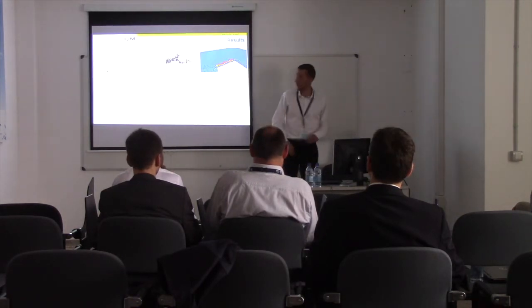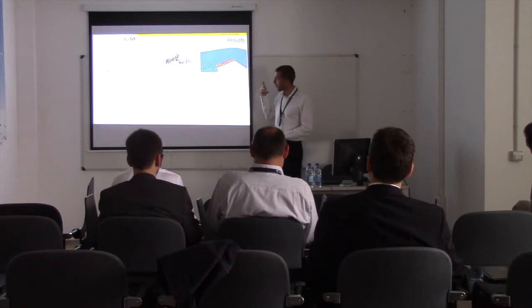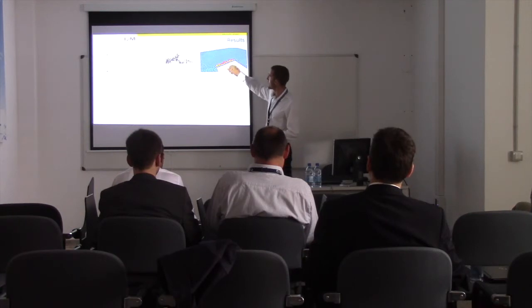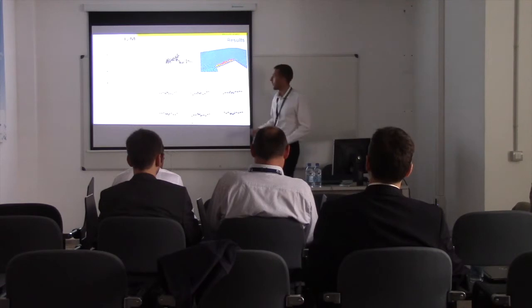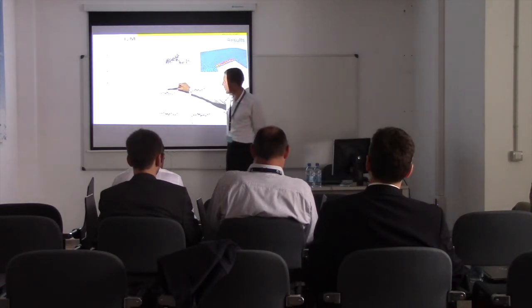And we observed that when the recoater impacts this melted part, we have a compaction of the particles around it, which can be associated with an evolution of the packing density, as you can observe here. So this is the first layer. In gray here are the third layer and the sixth layer.